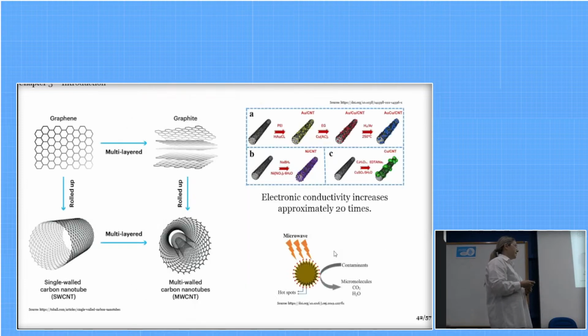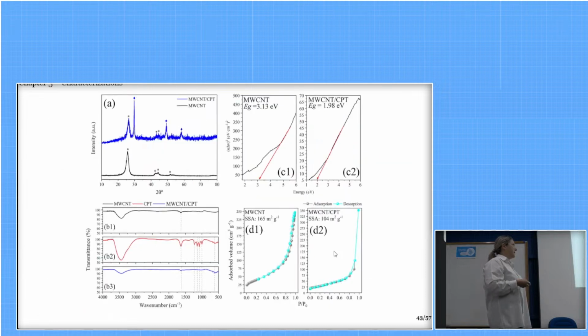Here, we tested the hypothesis for the use of more ordered carbonaceous structures, as the literature reports that the loading of metallic particles onto multi-walled carbon nanotubes can increase electronic conductivity by approximately 20 times. So, supported by this theory, we synthesized this catalyst and showed the successful coupling between these two materials, preserving the graphitic phases of the multi-walled carbon nanotubes seen in the preceding sample, shown here.